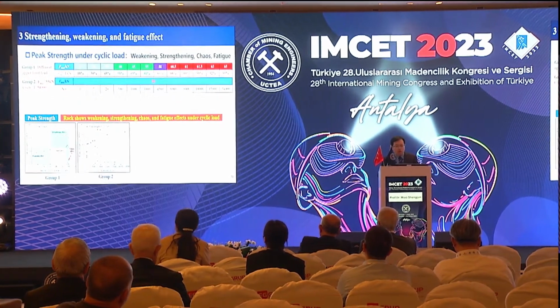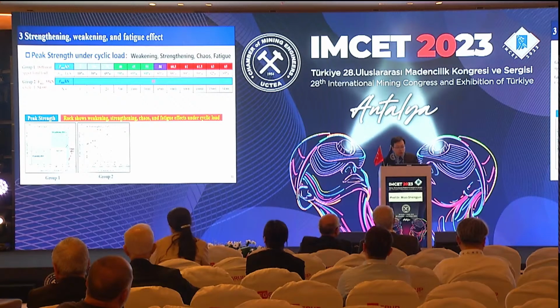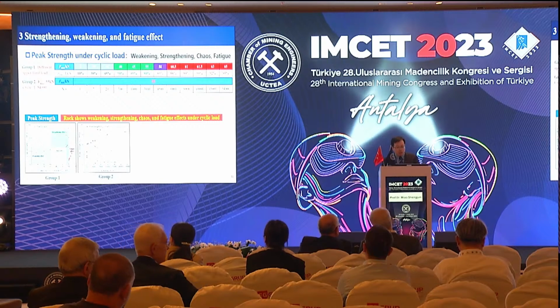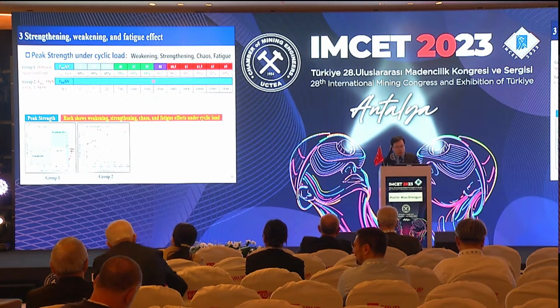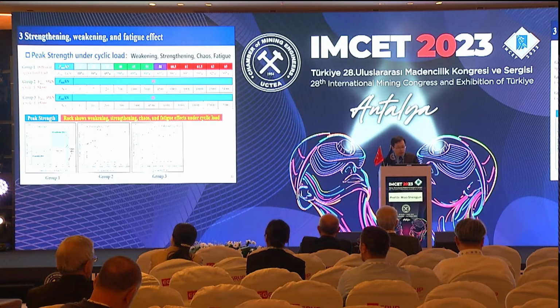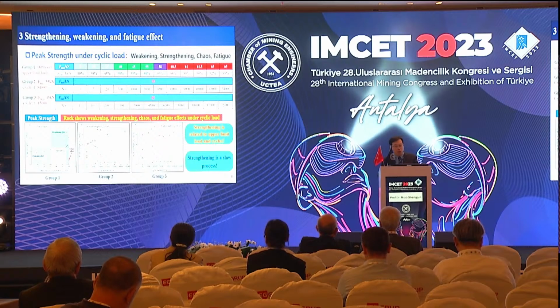For the upper limit load of 55 kilonewtons, it can be observed that when the cycle number is less than 300, the siltstone's peak strength is lower than the UCS. As the cycle number increases, the peak strength rapidly increased and then stabilized. And the results of Group 3 are almost consistent with Group 2. This indicates that the siltstone strength is influenced not only by the upper limit load, but also by cycle number. Moreover, cyclic loading initially caused damage to the rock, and then continuous closure of cracks results in a strengthening effect, which is a slow cumulative process.